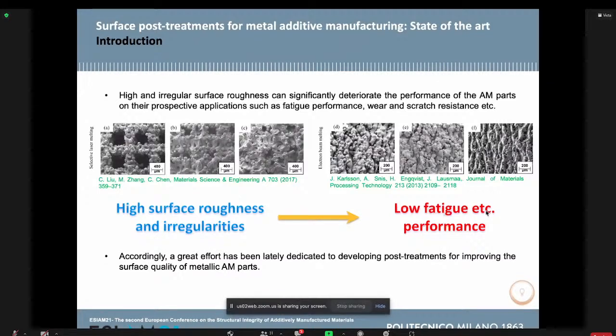It is well known that additive manufactured materials mostly have poor surface quality and irregular features on their surfaces, which can be characterized by partially melted and unmelted powders and also spatters. Here you can see examples of two different technologies that we use for fabrication: selective laser melting and electron beam melting. In both of them, we can see lots of defects on the surfaces. And as you know, most mechanical failures, especially fatigue behavior, are very sensitive to the surface properties. If we have lots of surface defects, we are going to get low fatigue performance for the material.